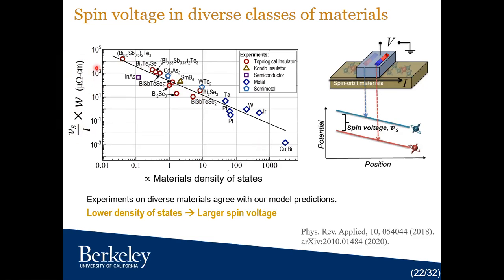Then what we observed is that all these measured data follow a trend that is inversely proportional to the density of states of your material. And that was another major conclusion of our theoretical model. And all these experiments are following that theoretical prediction.